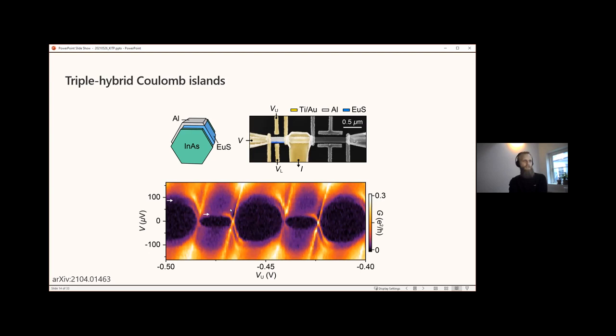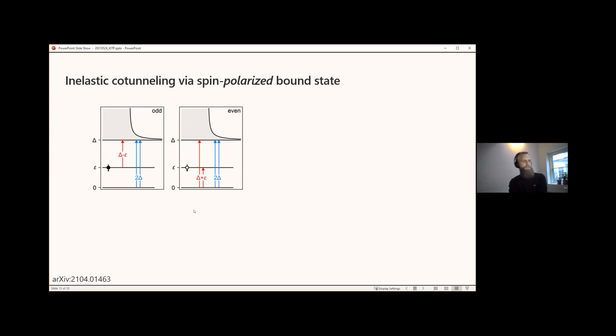But in addition to that, we also see some steps in conductance at certain energies that alternate from diamond to diamond. We associate these steps with inelastic cotunneling processes. And to understand them better, we developed a theory describing transport through a spin-polarized bound state. So when the island is odd-occupied, we have a single subgap state, or we consider a single subgap state that can be occupied by a single spin, and the counterpart is spin split and is taken out of the picture, essentially.